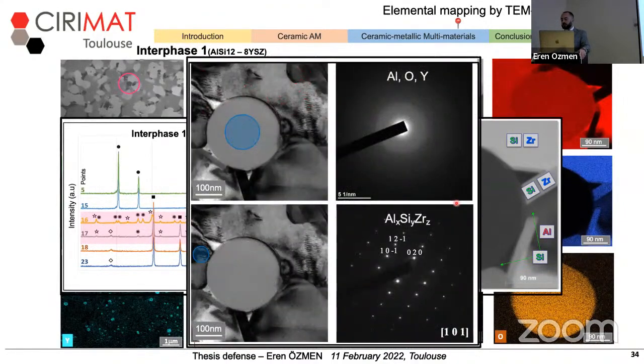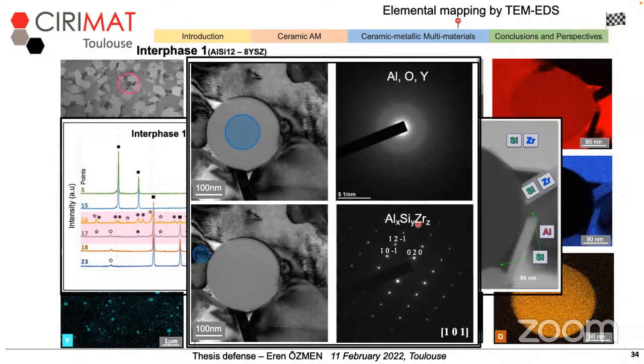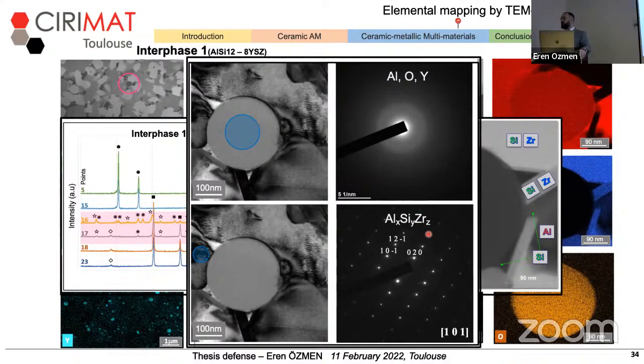So here I choose a method with which I can study the crystallinity of these phases appearing in the structure. When we choose two areas, one aluminum, oxygen, yttrium rich, and one the ternary phase, and use selected area electron diffraction, I see that while the ternary phase is giving diffraction patterns, the yttrium-rich circular area is not giving any diffraction patterns. So that means this structure is amorphous. That might be the biggest indication that it's not detected in XRD measurements.